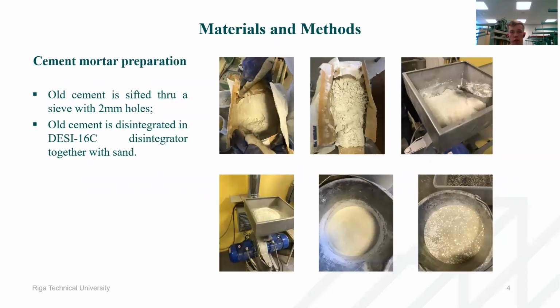For this purpose, all the old cement was used. All cement was meant for the cement mortars. First of all, it was sieved through sieves with 2mm holes, and afterwards, half of that cement was put through the disintegrator DESI-16C. As you can see on the bottom side, here is the disintegrated composition of the mortar, and here is non-disintegrated composition of the mortar.